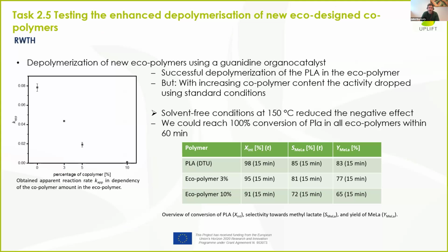The eco-designed polymers were also tested under the guanidine catalyst, and here, strangely, in the beginning there was an opposite trend, where increasing the amount of PHPA, the degradation of PLA decreased. But the Haken group basically overcame this issue by increasing the temperature. Reaching a temperature of 150 degrees Celsius, they managed to fully degrade the eco-designed polymers within 1 hour.